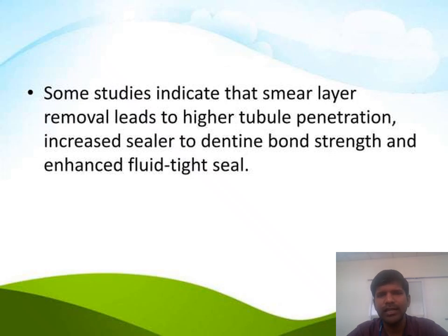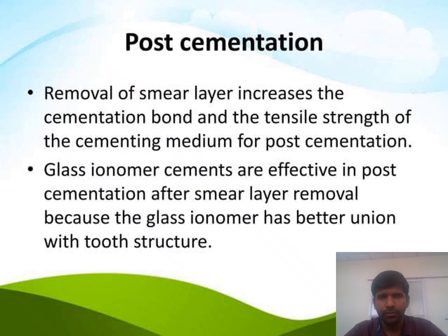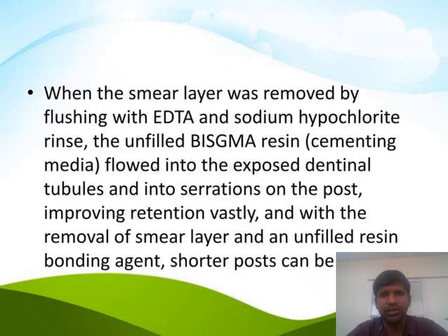Some studies indicate that smear layer removal leads to higher tubule penetration, increased sealer to dentin bond strength, and enhanced fluid tight seal. Coming to post cementation, removal of smear layer increases the cementation bond and the tensile strength of the cementing medium for post cementation. Glass ionomer cements are effective in post cementation after smear layer removal because the glass ionomer has better union to tooth structure.